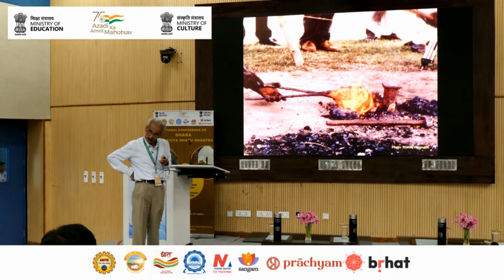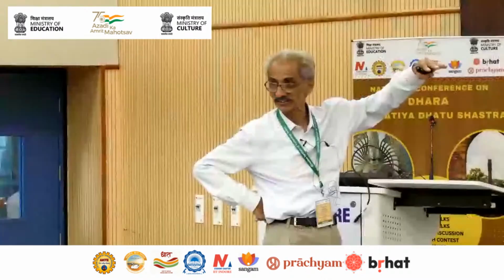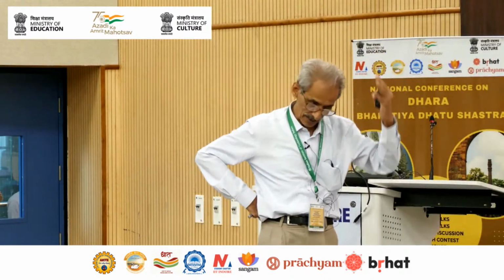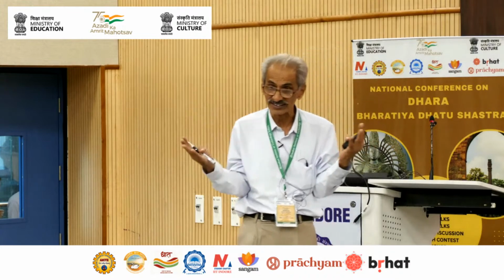No, you can go. It depends on the blowing and the amount of air which you have put. It depends on the size of the furnace. You go higher. You form the iron, and then you spend enough time inside in charcoal. You pick up carbon, and the melting point falls. So Chinese furnaces are longer, taller, for cast iron melting. Because Chinese were always very, very good in casting. So they always cast it, and then of course they would decarburize for whatever steel, like they used to do in blister copper and so on.